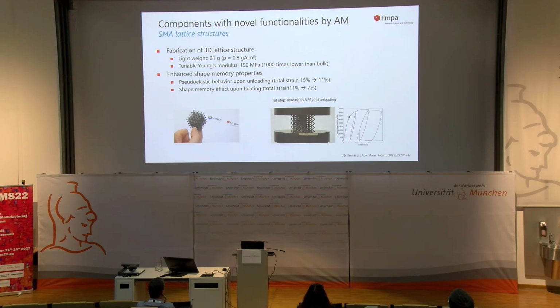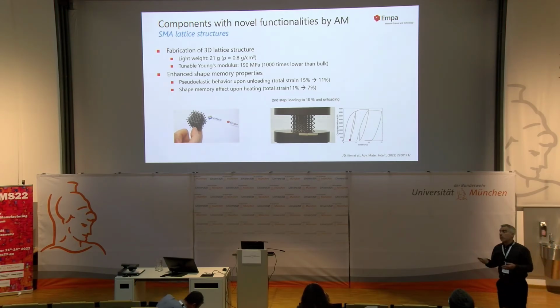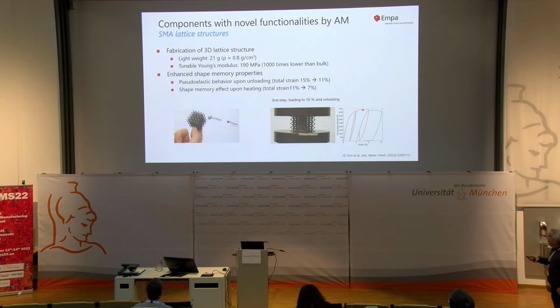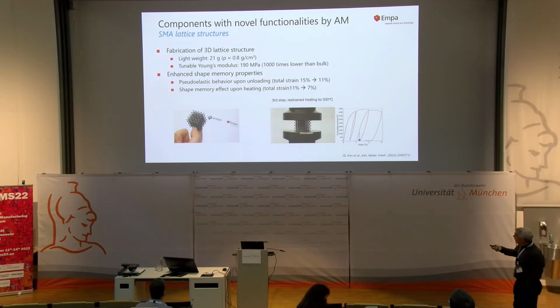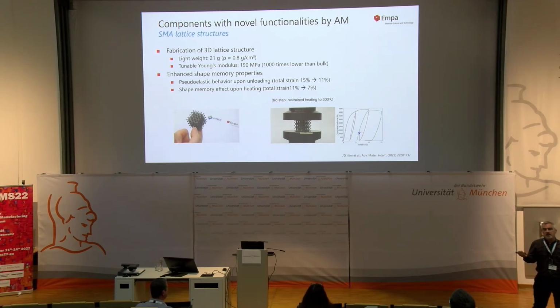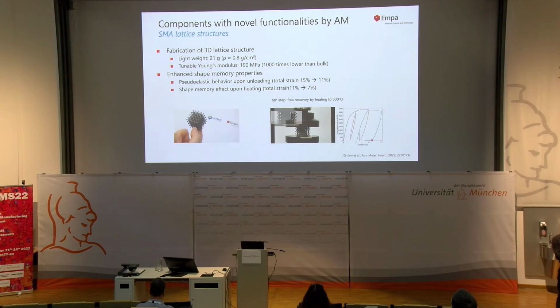We went also into the fabrication of more complex 3D lattice type of structures, which are of course lightweight because there is not much material. And with the geometry, we can tune, for example, Young's modulus. But with these structures, we can amplify the shape memory properties. So, for example, this pseudoelasticity can be enhanced by a clever design of the lattice structures, which we could show here. And what is also interesting, these lattice structures, even if they have been deformed, of course not to very, very high strains, we can heat them and they will recover their shape afterwards.